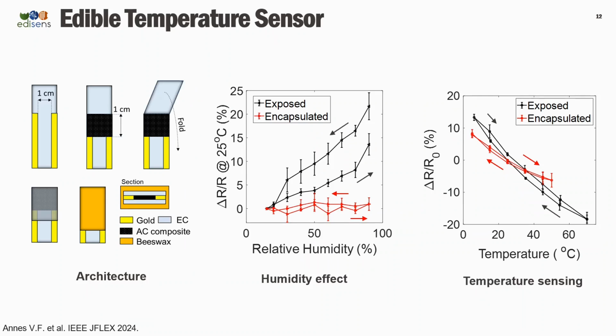And the final application that I would like to show you today is temperature sensing. Activated carbon is very well known to be affected by temperature, but also affected by humidity. As you can see in the central picture, just our coating is the black curve. So this is sensitive to humidity and also has some hysteresis, which is not ideal, but it is also very sensitive to temperature. And carbon, differently from metals, has a negative temperature coefficient. So when you increase temperature, the resistance will go down.